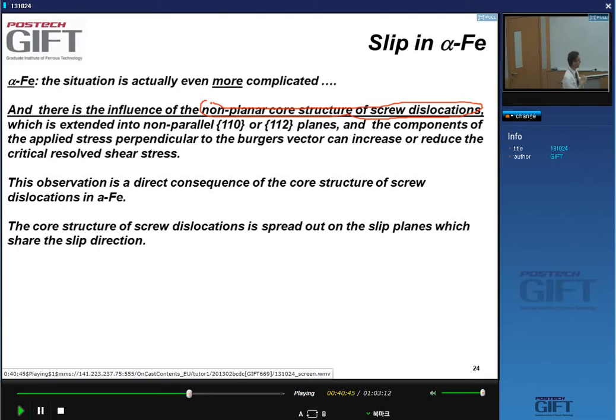And as a consequence, there is a force normal to the slip plane. So non-shear forces, normal forces, have an influence on the critical resolved shear stress. And that's a violation of Schmid's law, which says that you only have to consider shear forces. Okay? So what do we mean when we say the core structure